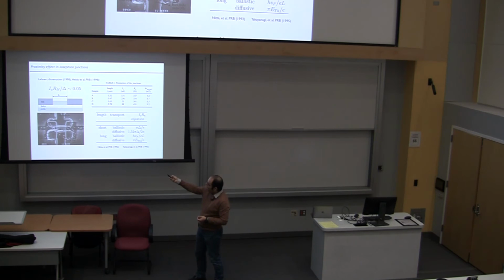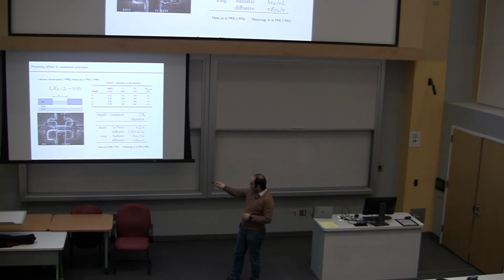If you normalize it with the gap, they get 0.05. And that was kind of the standard number for most of these junctions. What you expect for a short ballistic junction is pi delta, right? Delta is the gap and pi. So you needed this to be 3 point whatever, and now it's 0.05. That's not good. Something is wrong, right?